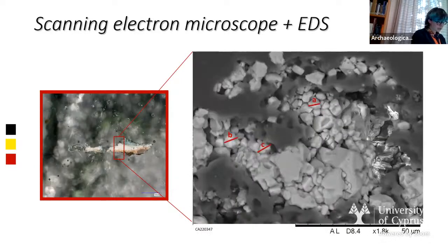Afterwards, we measured the size of the grains to define if the paste had been treated with heat or not, so if they were real clusters or not. We did this employing ImageJ software. To be considered real clusters, the grains of calcite should have a size smaller than 1 micrometer, because in true clusters, calcite grains are recrystallized at high temperature. Hence, they appear smaller and more regular in shape and size.